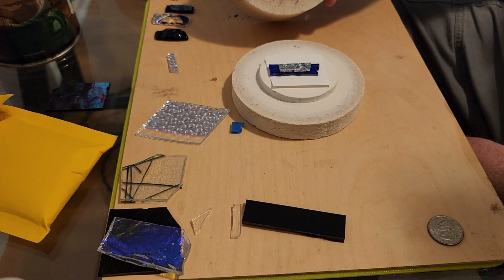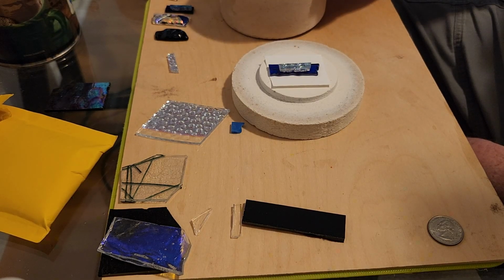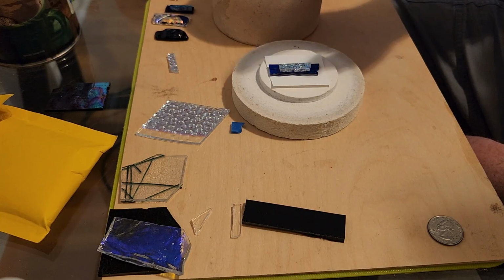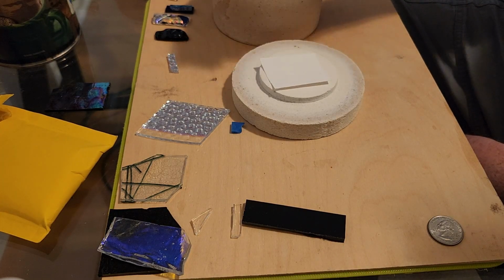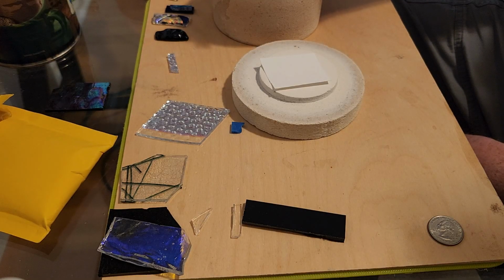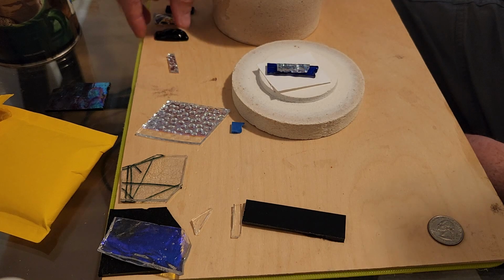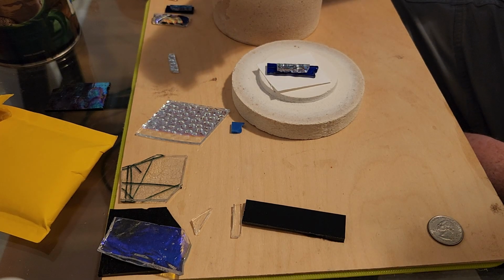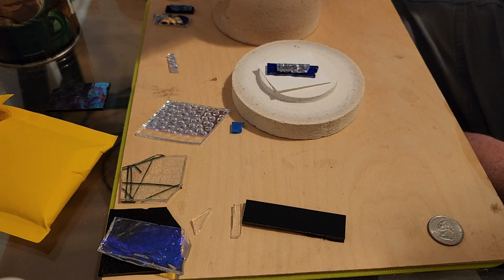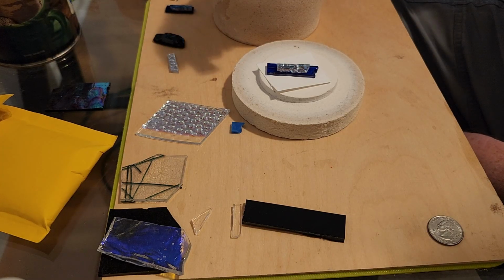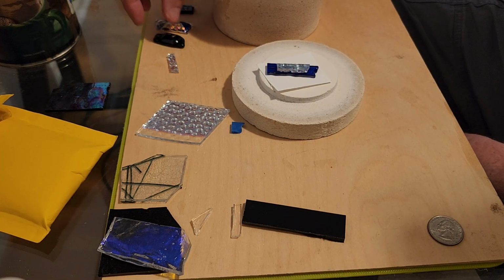And it should be a very, very light orange. If it gets to the point where it's bright orange, bright red, or oh my goodness, white, the problem you're going to have there is you've overfused. If you're lucky, the only thing you'll do is you can literally melt the metal in the dichroic and you lose all of the shininess, the reflection. That's a little bit of what happened here. This got a little bit too hot and it's not as reflective as, say, something like this, which is only partially melted and you can see has quite a bit of a reflection to it. So that's one thing that will happen.